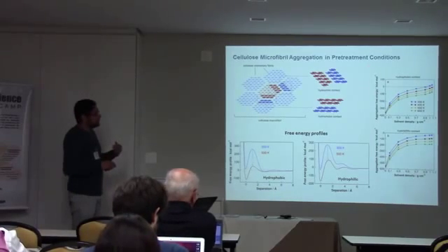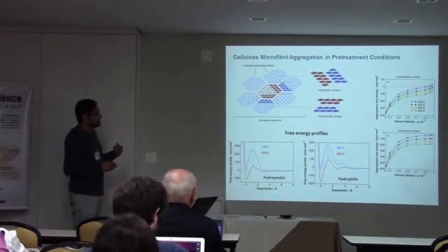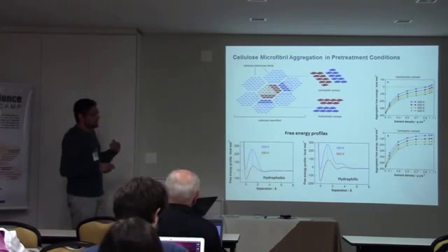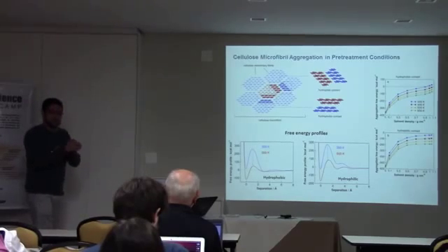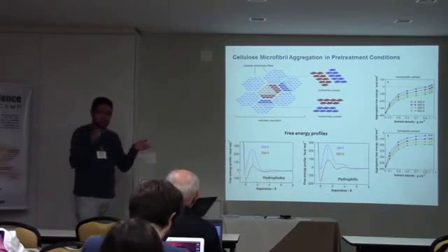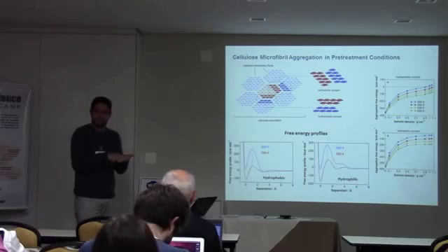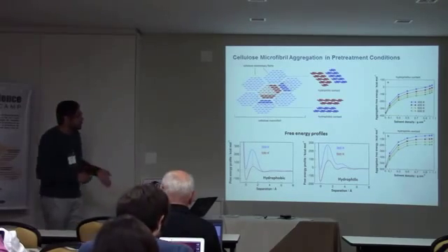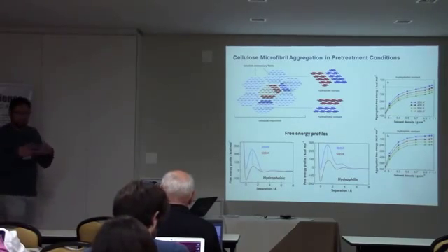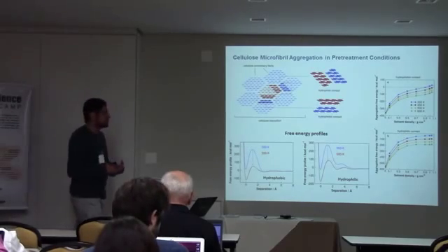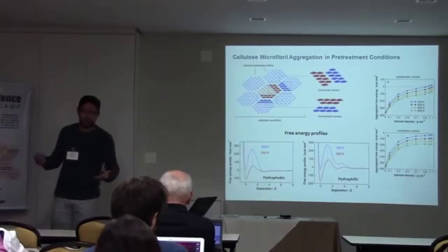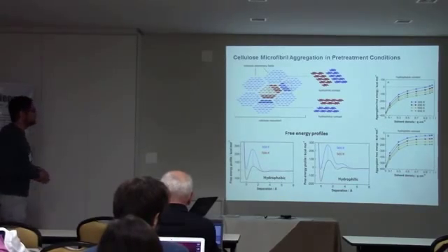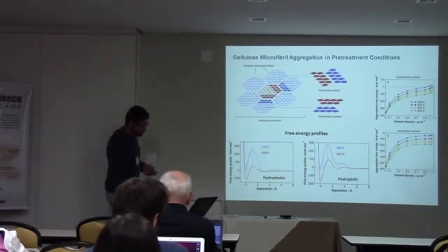For example, at 300 kelvins, the free energy of aggregation goes above 0, which means that cellulose doesn't aggregate through the hydrophobic surface in room conditions, but it can aggregate in room conditions through the hydrophilic surface. But when you increase the temperature, everything aggregates, even the hydrophobic contact.